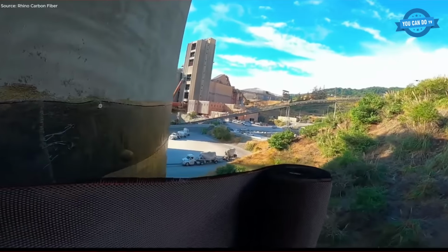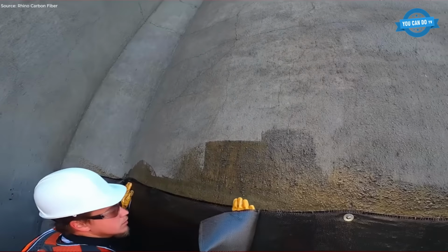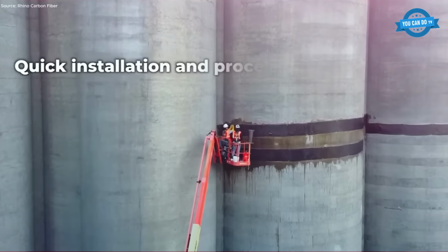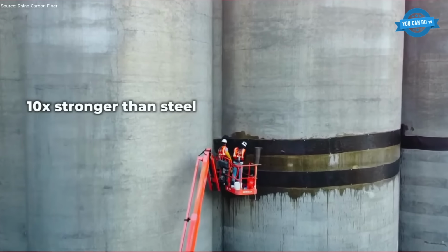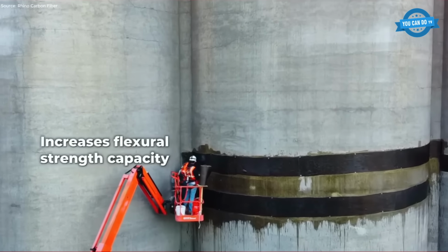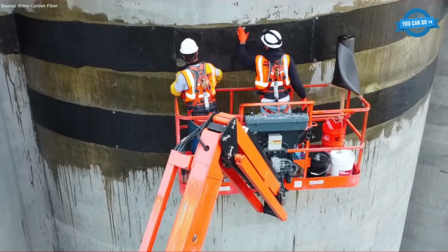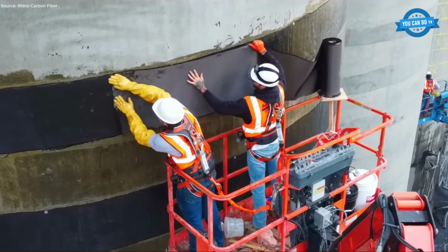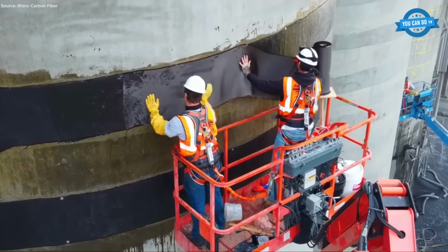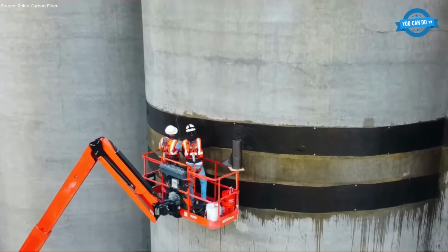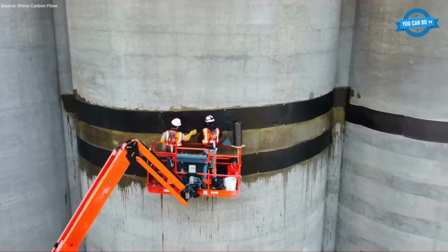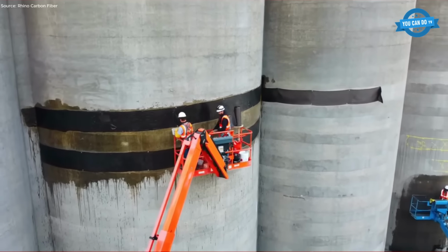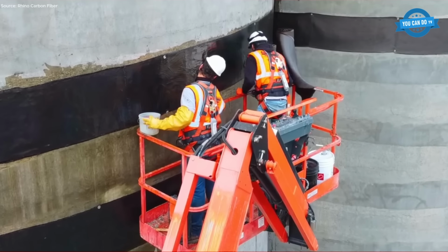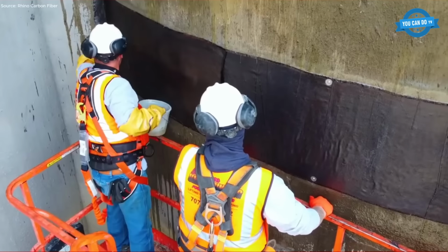Rhino carbon fiber systems utilize externally bonded carbon fiber reinforced polymer to restore and enhance structural performance. The application process begins with detailed structural assessment, surface cleaning, laitance removal, and crack injection repair if required. An epoxy primer is applied, followed by saturation resin and placement of carbon fiber fabric around the silo circumference in calculated wrap patterns based on engineering design.